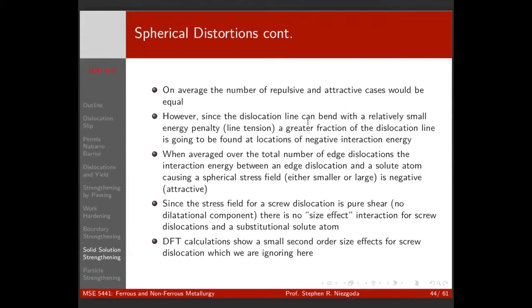This is the same thing that we'll see happens in GP zones in aluminum, which are clusters of atoms, right? We have a similar type thing. So there's one subtlety that we need to take into account, right? This was for an edge dislocation. So the stress field for a screw dislocation is pure shear. So there's no dilatational component, right? So that means there is no size effect for pure screw dislocations. Only dislocations that have an edge component feel a size effect from substitutional solid solutions. Right. There's some other small things you can get from DFT calculations, like electronic interactions and things, but we can ignore those for right now.